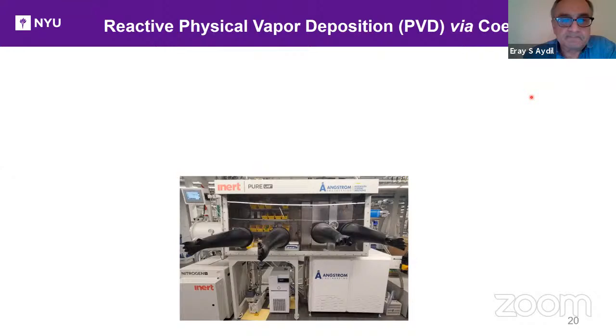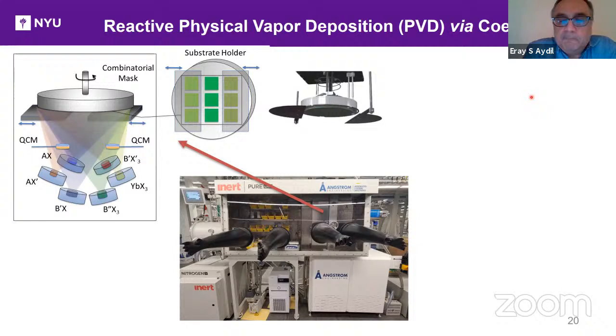So we deposit these using reactive physical vapor deposition via co-evaporation of the precursors. I call it reactive physical vapor deposition because we physically evaporate the salts, but upon landing on the substrate, they react. So it's not physical vapor deposition like you would do to metals. There's a reactive component to it. We have a PVD chamber that's glove boxed, and inside it there are six sources, each with independent quartz crystal microbalances and a combinatorial mask that allows us to look at various compositions really rapidly. So we can move this mask, these knife edges, over samples either discretely or continuously to put gradients or deposit matrices of 3x3 or 4x4 samples and produce libraries of various compositions.